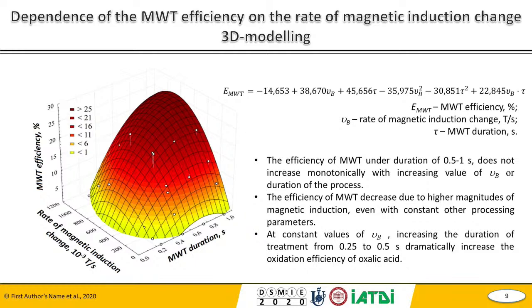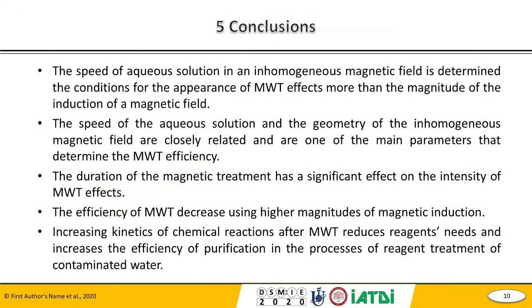At the processing time from 0.5 to 1 second, the oxidation efficiency does not increase significantly, and further increase in the duration is technically unreasonable. So on the next slide, you can see the main conclusion about our results.